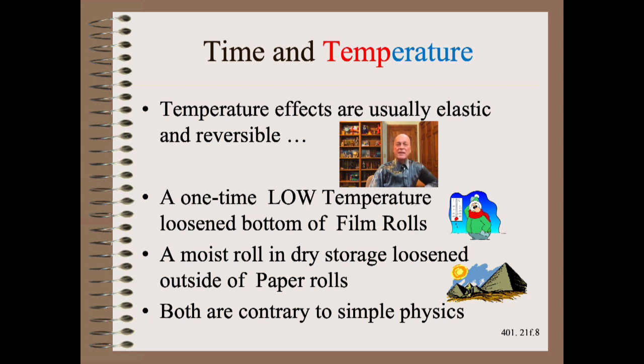In the film example, we would expect to tighten, not loosen, the film rolls down near the bottom due to thermal contraction against an unyielding core. However, there are irreversible strain changes on this curious film that are on the order of parts per thousand. Still, small strains can have a huge effect in web handling.